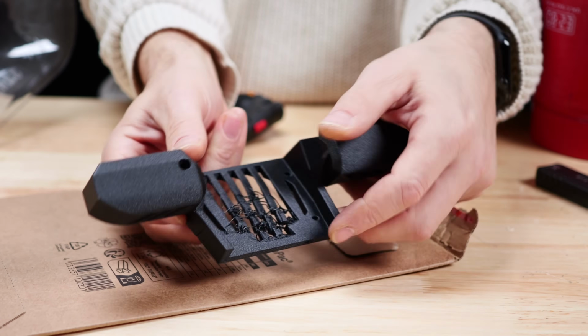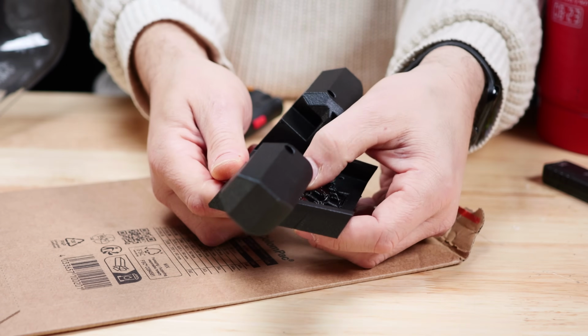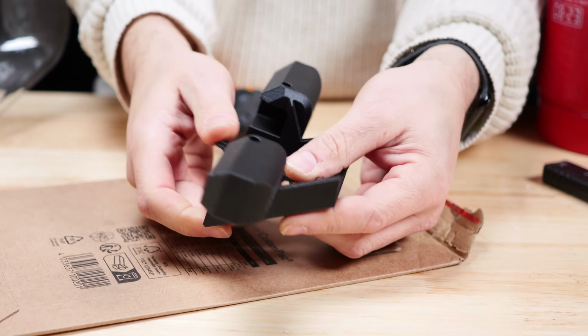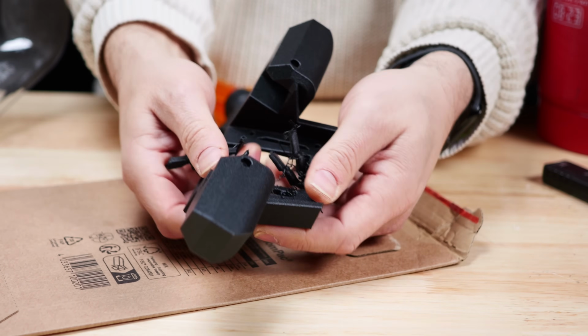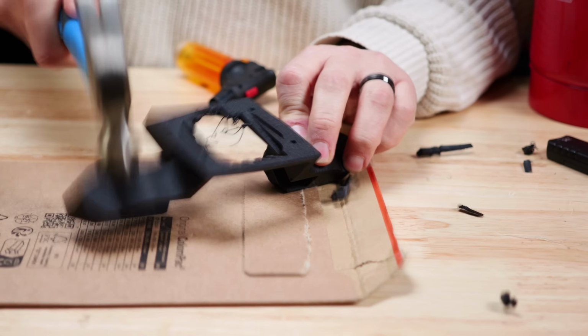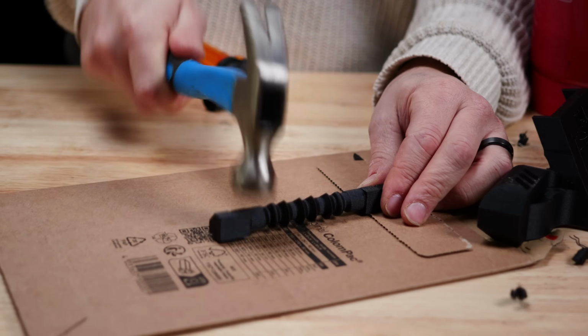But there was one thing that really did surprise me. See, even with the glass fibers, this stuff is actually very flexible, especially where the part is thin. Now don't get me wrong, the thicker parts are definitely much more rigid than normal TPU, but as you can see, these thin parts here were so flexible that they actually moved under the print head during printing, causing local layer shifts. Now because of this, you will want to account for this level of flexibility both in the design phase, when you think about how thick perimeters should be, and when slicing. But before I hand these over to my son for some real-world testing on his Death Racer, here's some gratuitous durability testing for all of you.